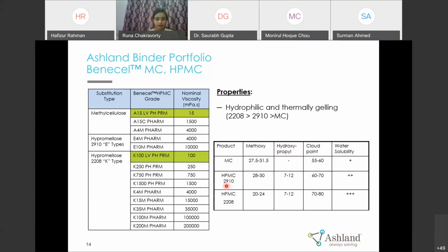So here, the first two numbers of HPMC, like 2208 for example, the 22 tells us about the substitution of the methoxy group. Here you can see that methoxy group substitution is between 20 to 24. So 22 is the mean, it comes between 20 and 24. And 208 tells us about the substitution of the hydroxypropyl group, which comes between 7 to 12.